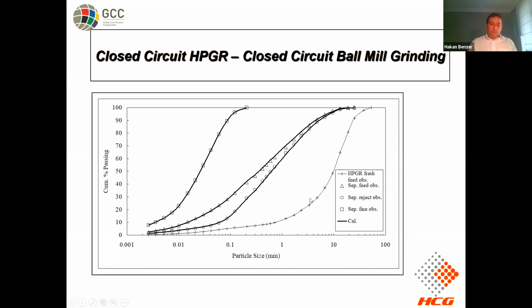You can see the full size distribution around the system. This is the typical HPGR product from a closed circuit. You may notice that we are receiving a steeper size distribution. The reason is that the fines generated are immediately pulled out of the system by the air classifier, and this gives the energy advantage of the equipment.